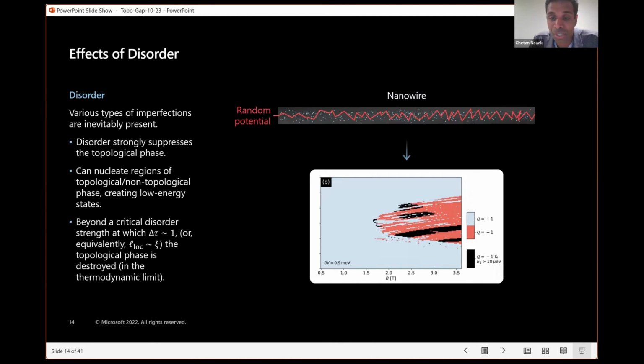This is the situation. This is a finite length wire. Now, in an infinite wire, there's no gap, because the gap will fill in with localized states. This is a wire of finite length, like 3 microns long, which is, as it turns out, how long the wires in our system are. So many of the states at this disorder value have localization lengths that are longer than the wire length. And so effectively they're delocalized states at the system size. So in a wire of this length for this disorder level, there is actually an energy gap. Okay, it doesn't fill in with localized states. And this is an energy gap greater than 10 microvolts.